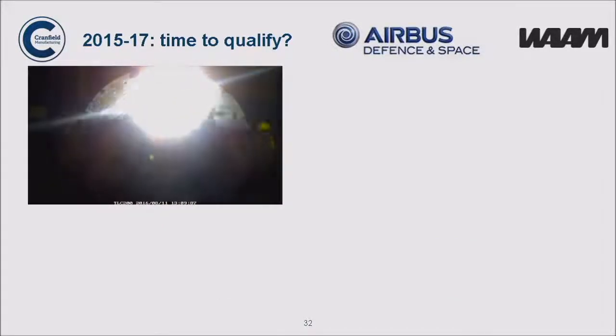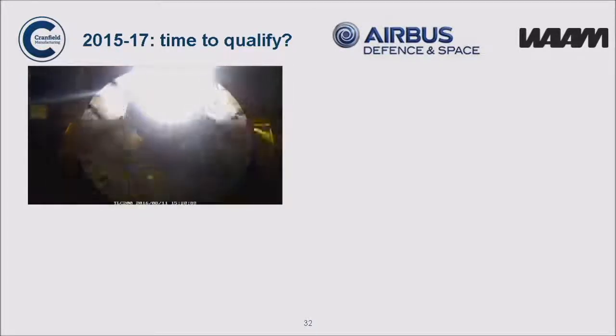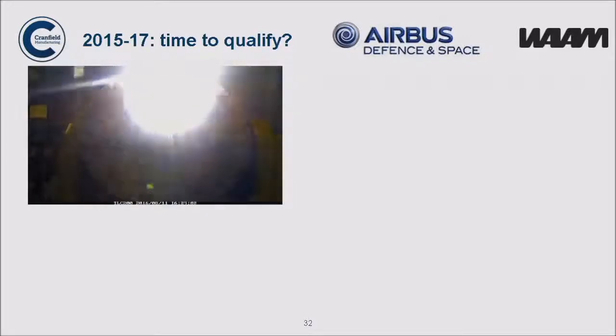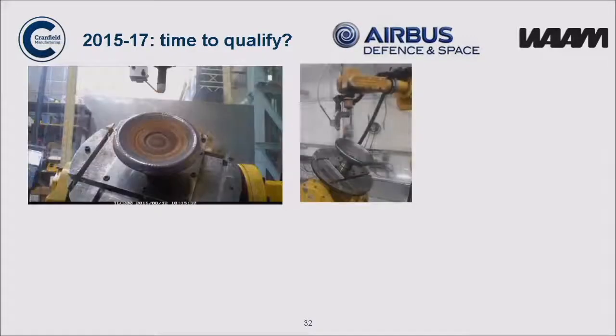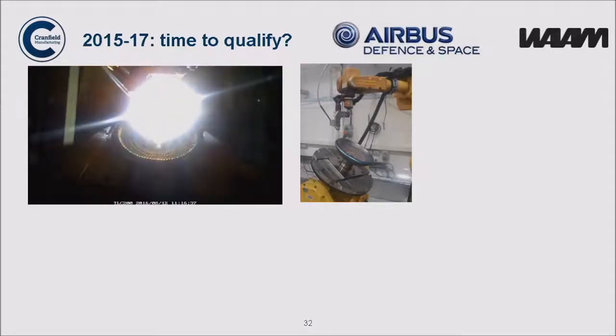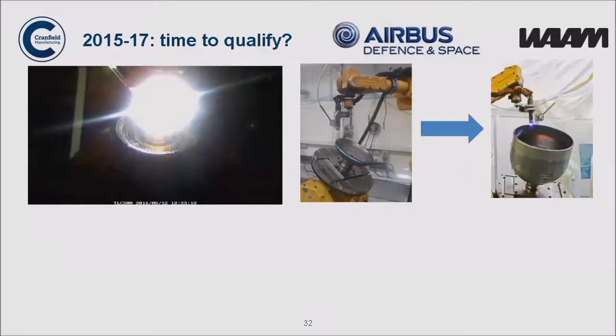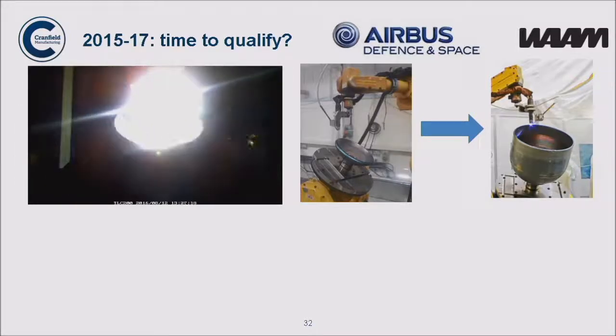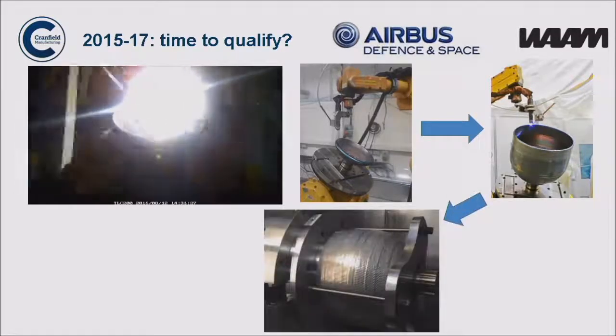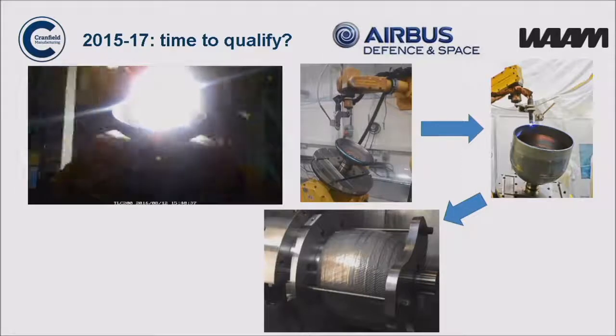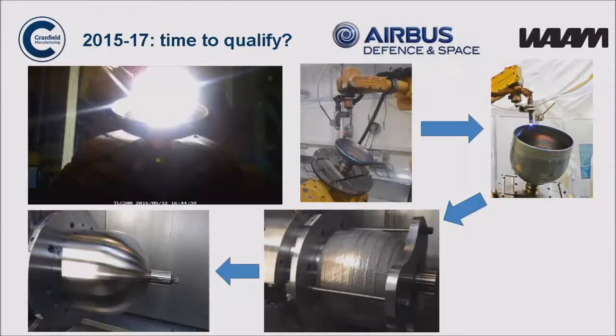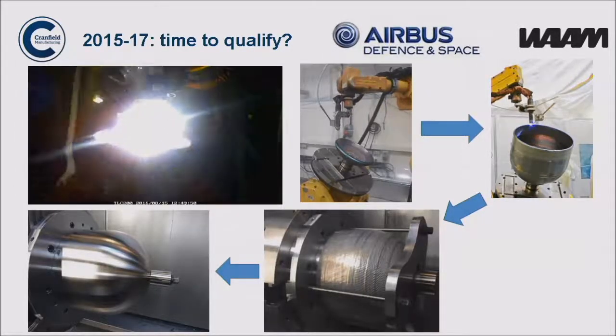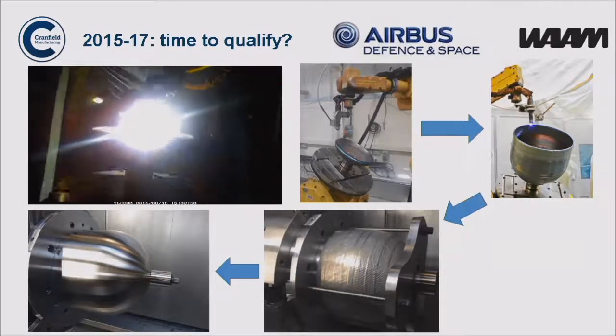So we set about building this using the wire and arc process. So you can see a video. You can't see much at the moment because the plasma is very bright. You'll see more as it grows. You can see that this is the bottom section, which is quite thick. You can see a picture of it here. So we build up the bottom section, then we move through to building the cylindrical thin wall section. Once we've done that, of course, we need to get it machined. So we then put it on a lathe and do final machining. And you can see once you've done the final machining, it looks just like any other metal part, basically.